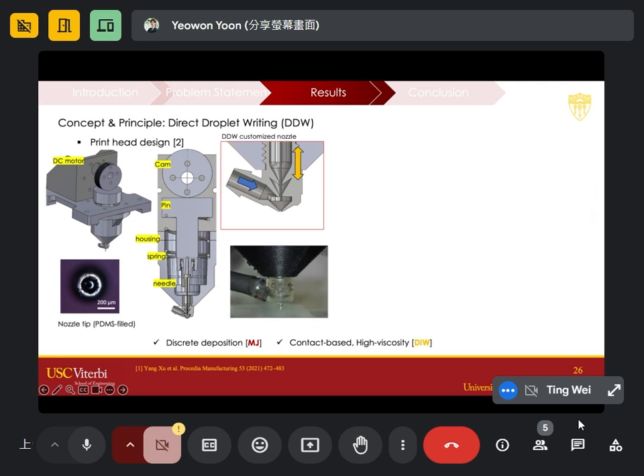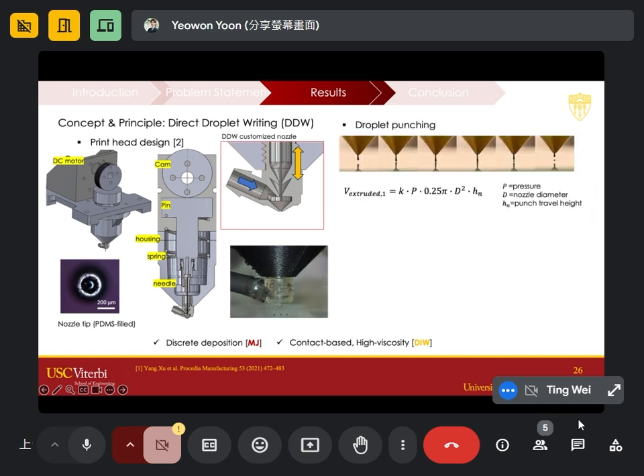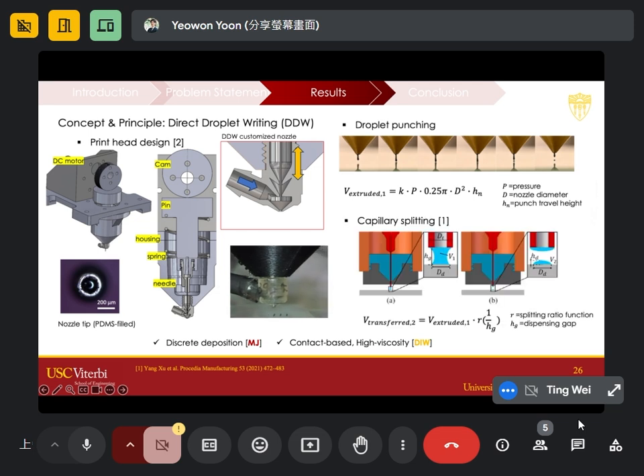So this is the key idea of dispensing viscous slurries onto the substrate. We have this kind of plunger machine that has a needle inside. The slurry comes into the reservoir, and the reservoir is fully filled. We have this mechanical cam motion, moving up and down with the spring, basically dispensing and tearing the material out. The key idea here is to punch the material out, so we call it droplet punching, where a few factors are determined by pressure, diameter, and travel height, but we're going to skip that. The secondary phenomenon happens once it transfers the material: the plunger travels back, and there we have a capillary splitting motion that determines the size. So it's a very discrete way of printing, highly contact based, and it can deliver extremely high viscous material, relying on material tearing, not on surface morphology.